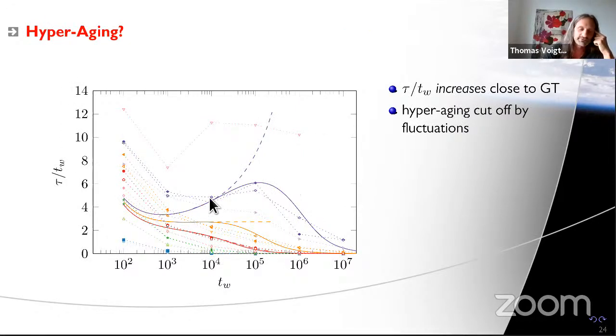And the way to see this is to divide the structural relaxation time by the waiting time. Now, if the structural relaxation time should actually grow faster than the waiting time, this function here should increase as a function of waiting time at some point. So this is linear-log now. And I did that with all the simulation data I could extract from the papers that you guys have written. These are two different simulation data sets that we're seeing here, but for comparable systems. And I would argue that there is an indication of an upturn here. And it would really be fascinating to have more data points there.